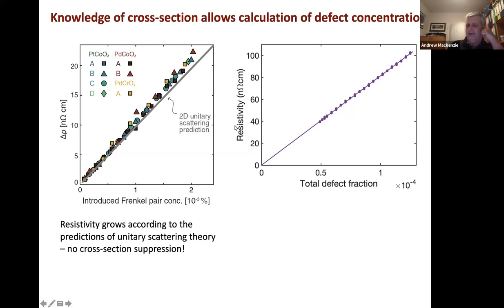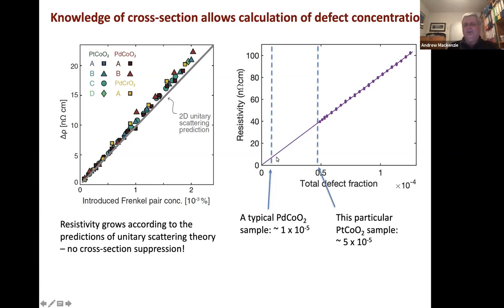So for that particular platinum cobalt sample, it's about 5 defects per 100,000 atoms, but palladium cobalt's better, and a typical good palladium cobalt sample has one or slightly fewer than 1 point defect per 100,000 atoms, just as you would have inferred from the mean free path when you started. And you know, we did that first mean free path estimate 10 years ago now. And when we did it, I'd never have believed that we'd have had precise experiments that allowed us to prove that that was taking place.